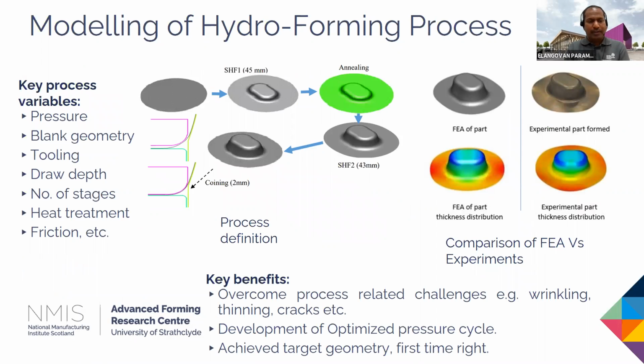Okay, so for the benefit of our customer, we used to do a lot of iterations through design of experiment by considering the key process variables, for example, the pressure, then the blank geometry, tooling, draw depth. So these are the process parameters we consider for our design variables. So for example, just for understanding purpose, when we increase the pressure during the forming process, especially the hydroforming one, we stretch the material too much, so due to that we may end up with rupture or even localized thinning. So we have to identify and optimize the pressure value, so this is quite important.